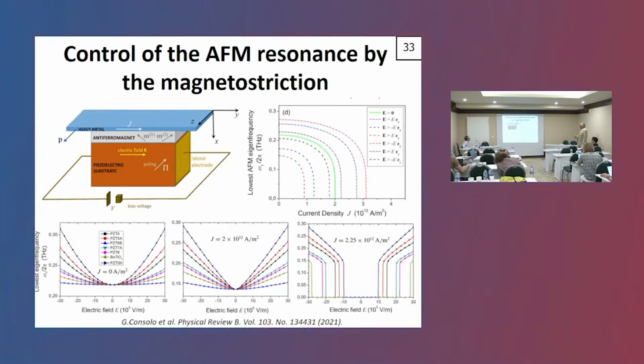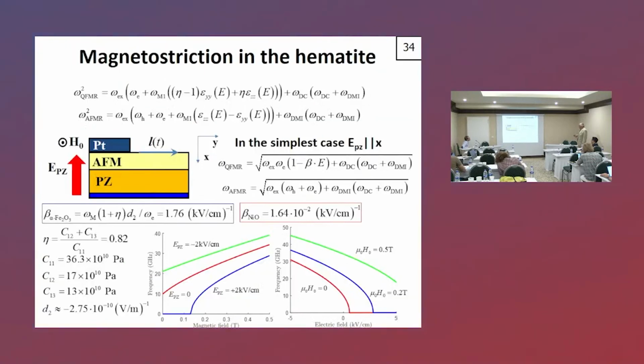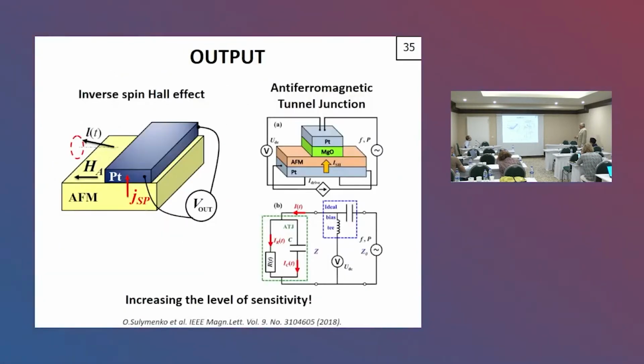And it can be shown that this magnetostriction is different for different crystals. For example, in nickel oxide, the coefficient of tuning is 1.6 times 10 to the -2 kilovolts per centimeter, while in hematite, it is almost 2 orders of magnitude larger. And you can extract the signal either by the inverse spin Hall effect or using the antiferromagnetic tunnel junction, which recently has been demonstrated experimentally.